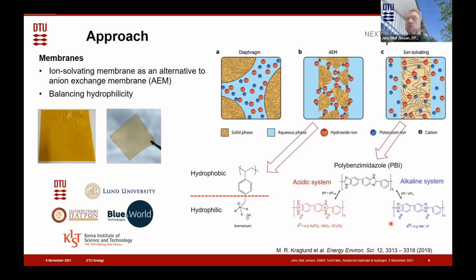And we have already demonstrated this performance of 3 amperes at 2 volts, together with our partners DLR and Jülich, and that was published in the paper. That's a reference here below. I think you get the slides afterwards, so if you are interested in more details, you can see about that. The thing here is that we have not solved everything. We've shown that this is possible, but the durability is not good enough. These cells break down way too fast. So that's something we are addressing in the project, to try to find other ways. We were looking at PBI also, but other polymers that should be more stable.